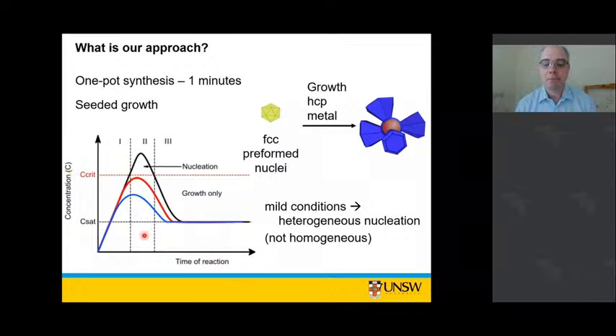So when we do these reactions, we really have to do them in mild conditions to have this very slow generation of ruthenium. One-pot syntheses can be very effective, or hot injection synthesis of nanoparticles, heating up synthesis of nanoparticles. They're excellent methods, and they tend to make nanoparticles sometimes in the space of just 1 minute. But when we're doing our coating reactions, we really take a lot of time. So we're very relaxed about it all. And we let the reaction react for a long, long time, particularly compared to just these few minutes.